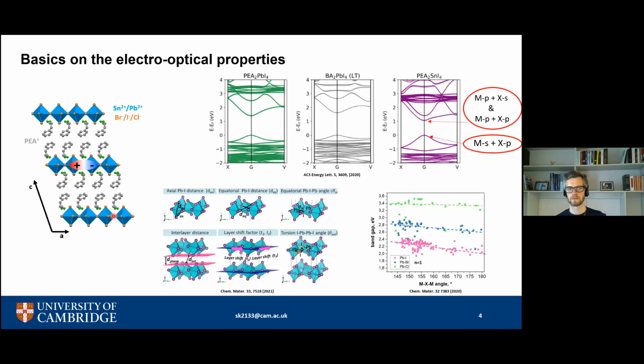If you put something very long, something very bulky in here, the electronic structure will change a little bit, but this is not due to hybridization of the electronic states. For example, if you see this metal halide metal bond angle, and the distortion here, you change the band gap energy a little bit, but it's mostly the halide in this case that really determines what you observe.